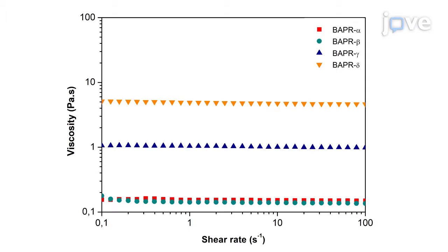The viscosity of the renewable resin is an essential parameter in the 3D printing process and is controlled by the monomer to oligomer ratio. Typically, a shear rate of 100 inverse seconds is achieved during the recoat of liquid resin in the printing process. All bioresins have a viscosity below 5 Pascal seconds and are appropriate for application in stereolithographic printing equipment.